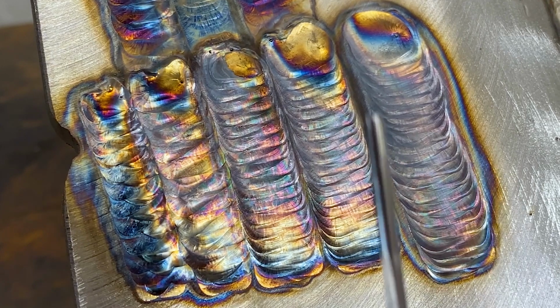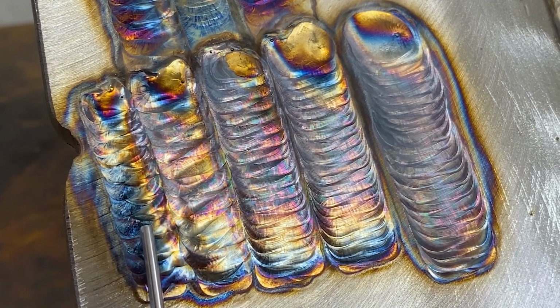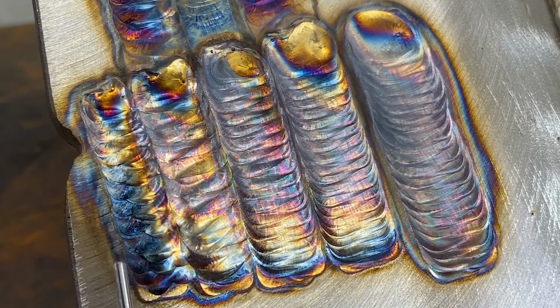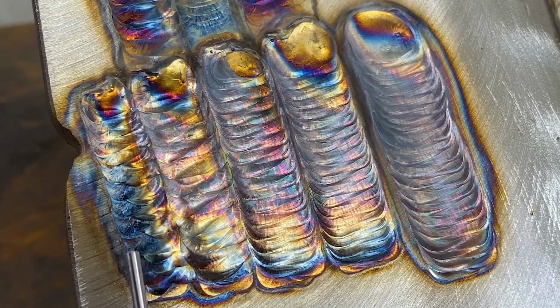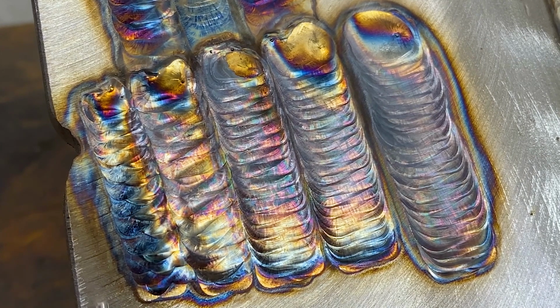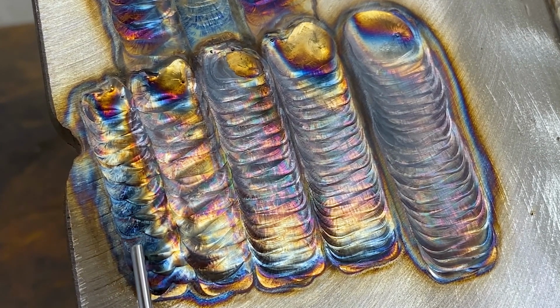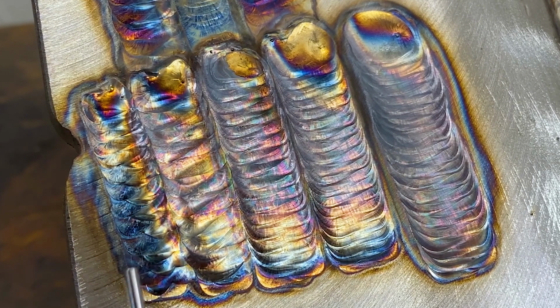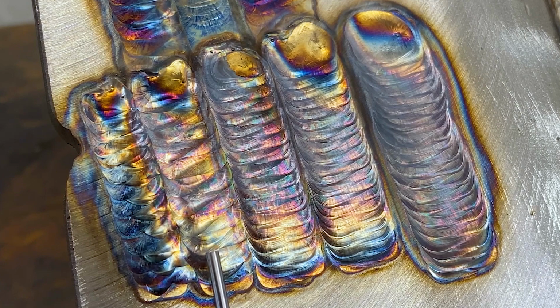Okay? So here we have, and this is on 3/8 plate running slightly uphill, 3/32 316 filler running at 90 amps. You can see it's real choppy. The movement was slower. It wasn't fusing with the base metal. It wasn't being consumed. And then we step it up to 120 amps.